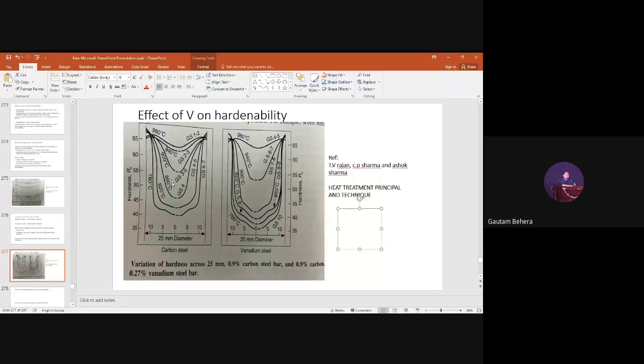You compare the curves. You compare the curve of 780 degrees centigrade, for example, this one. You can see the curve is up to this. This is the hardness value 40, for example, at the center. But you can see at 780 for vanadium, at the center the hardness is less than 40. It is nearly 35 or less than 35, right? So what is the answer? The depth and distribution of hardness is greater here, but it is less here. This is uniform hardness at the surface and at the center. But here there is more change in hardness from surface to the center.